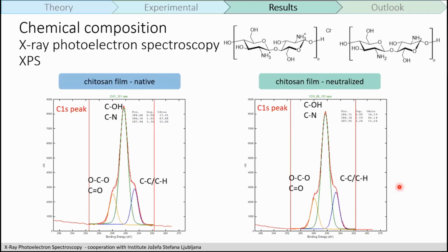Chemical composition: the XPS measurements were done in cooperation with the Institute of Jozef Stefan in Ljubljana, and they gave us excellent results from our native and neutralized types of film. From the C1s peaks from XPS measurements, we didn't see any drastic changes in the carbon-carbon bonding.